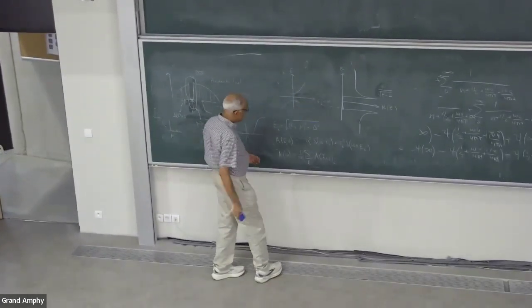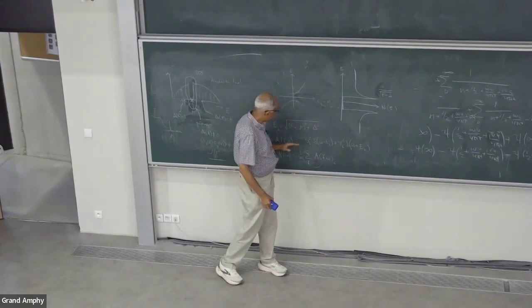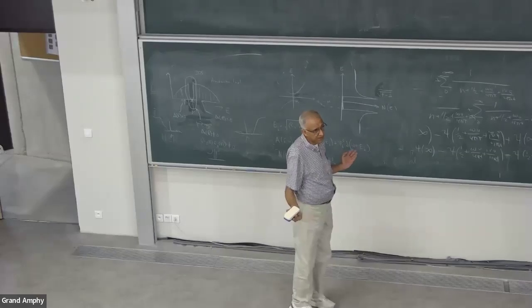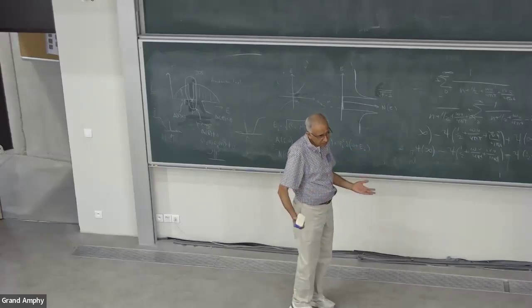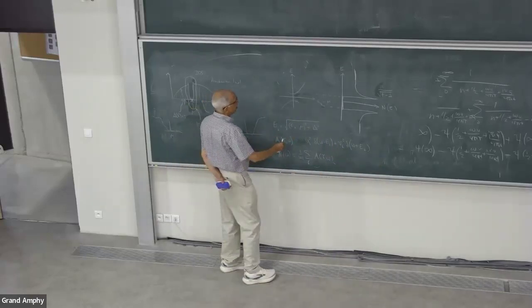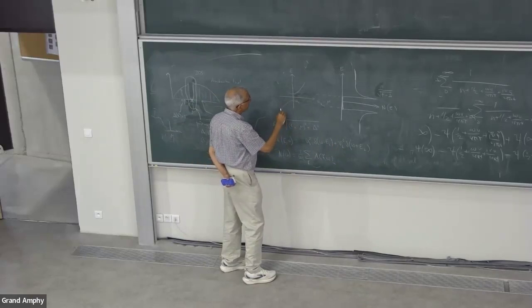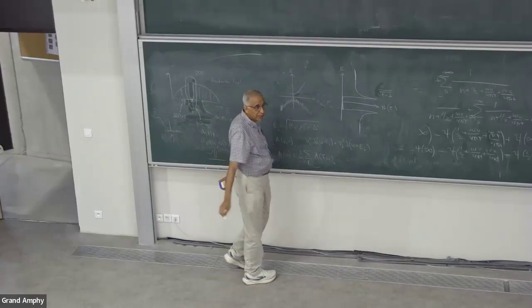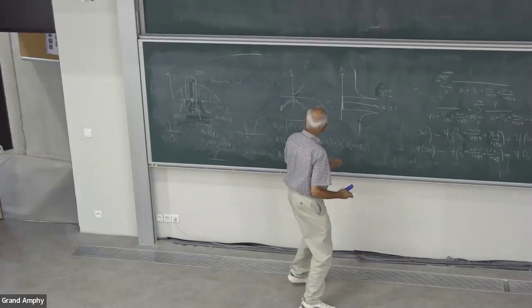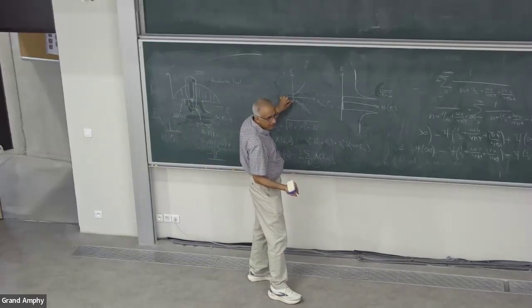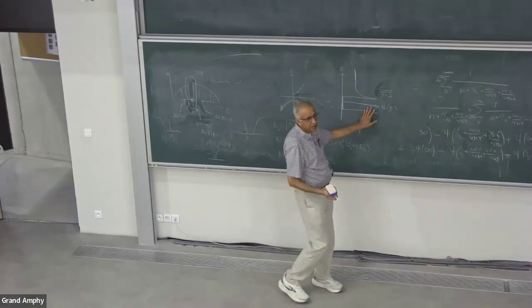But what do I mean by sharp quasi-particle? There are delta functions in the spectral function. But in many situations, you don't have delta functions in the spectral function. We know that from angle-resolved photoemission in the cuprates and so on. What happens is that this can become very broad. Now the question is how broad? What is the line width broadening? Because the broadening in energy of this line tells you the lifetime. The longer they live, the sharper the peak is. This will just destroy the peak.